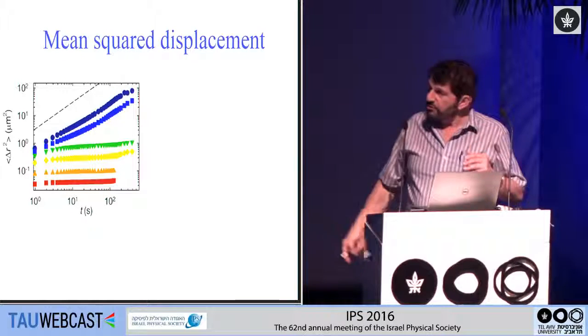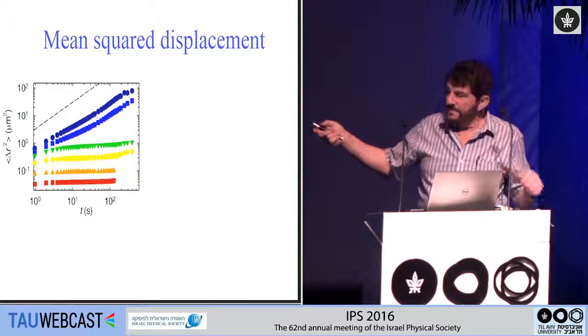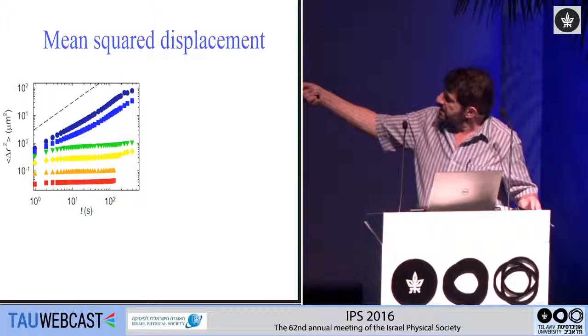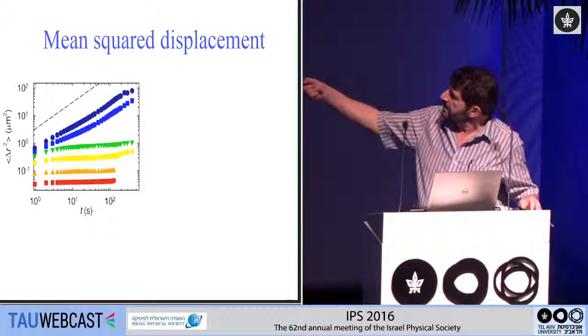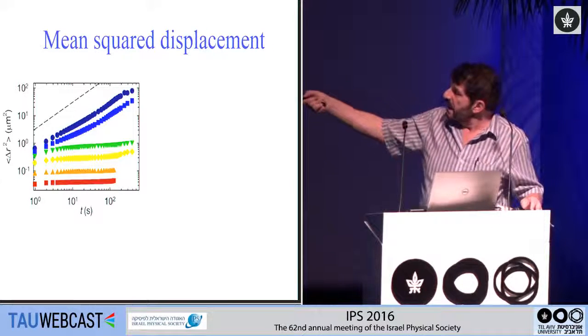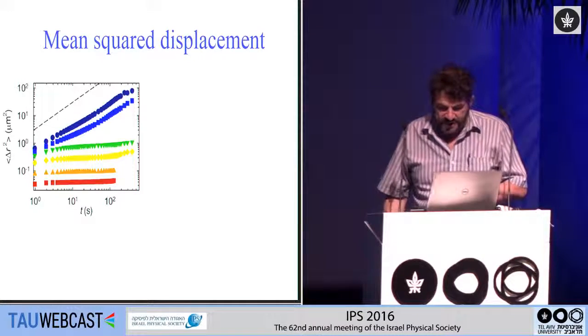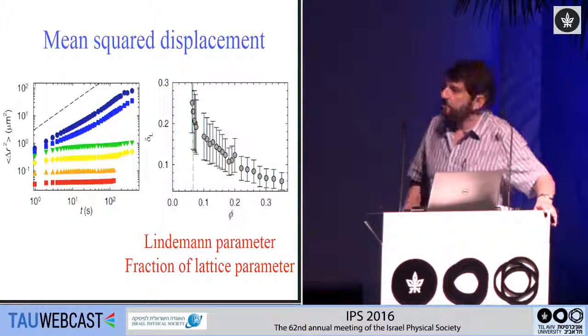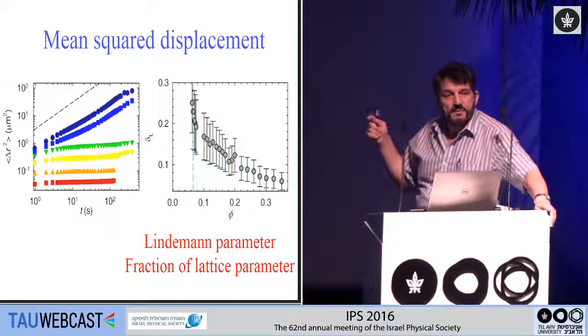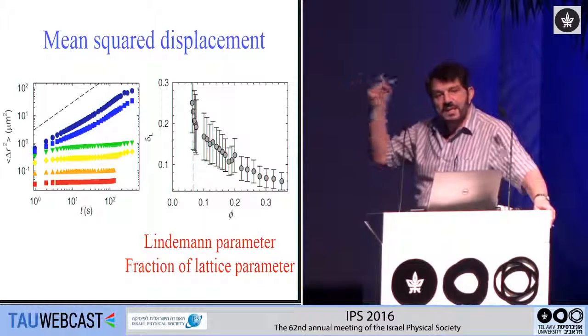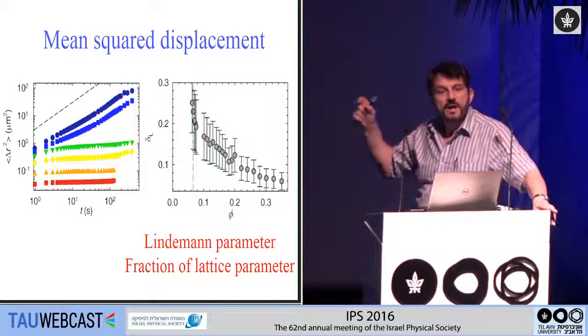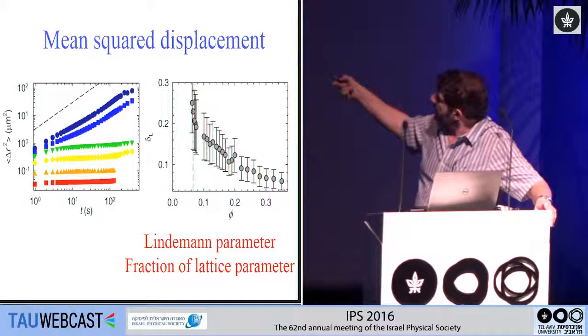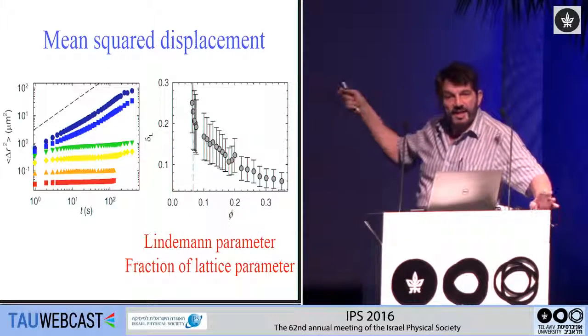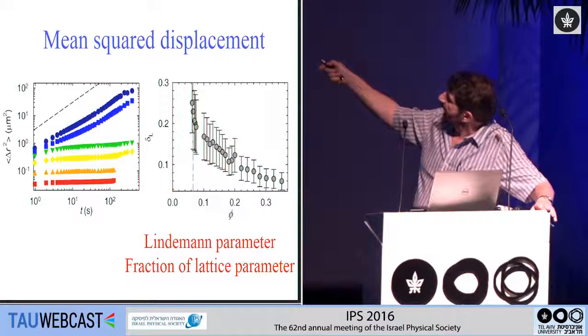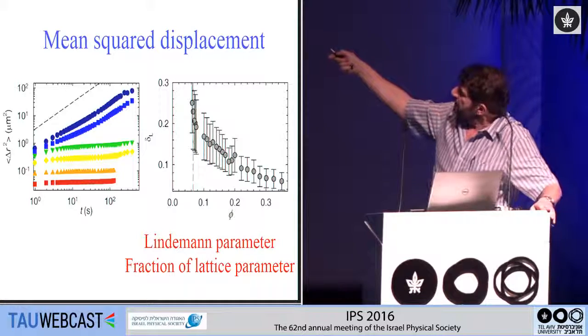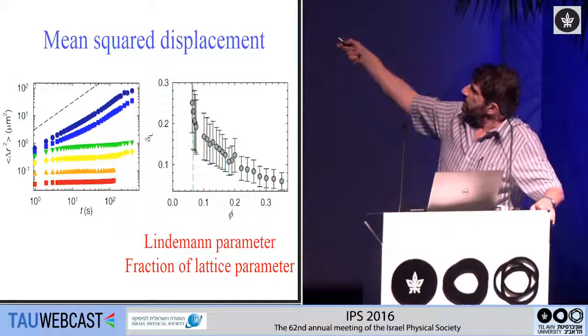Now, what's particularly interesting in this system is you can look at the amplitude of these fluctuations. These are systems that are getting lower and lower in concentration, and therefore approaching the melting, and you can see the fluctuations are increasing. And if you just plot the value of those fluctuations, this is what's called the Lindemann criterion. That's the amplitude of the fluctuations compared to the lattice constant, the ensemble average fluctuations. And it's shown here that as you decrease the volume fraction, that is, as you approach the melting, it increases and ultimately melts. But if you look at the values, if you can read these, this is 0.2, 0.25.